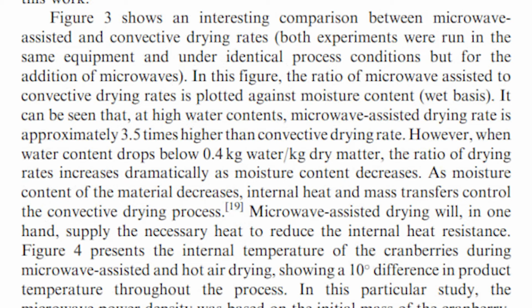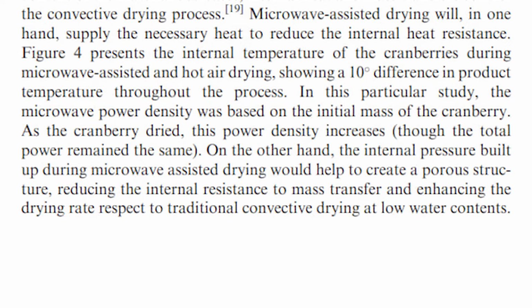It can be seen that at high water contents, microwave-assisted drying rate is approximately 3.5 times higher than the convective drying rate. However, when water content drops below 0.4 kilograms water per kilogram dry matter, the ratio of drying rates increases dramatically as moisture content decreases. As moisture content of the material decreases, internal heat and mass transfer control the convective drying process. Microwave-assisted drying will, on one hand, supply the necessary heat to reduce the internal heat resistance.